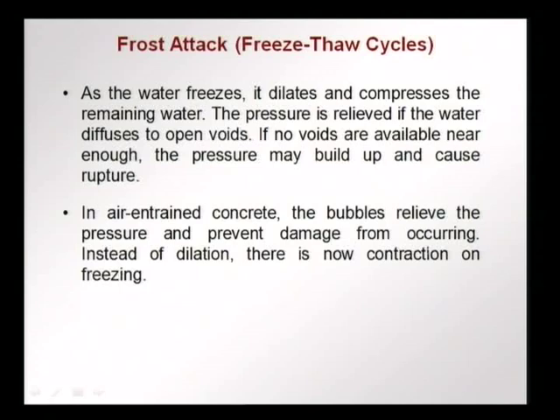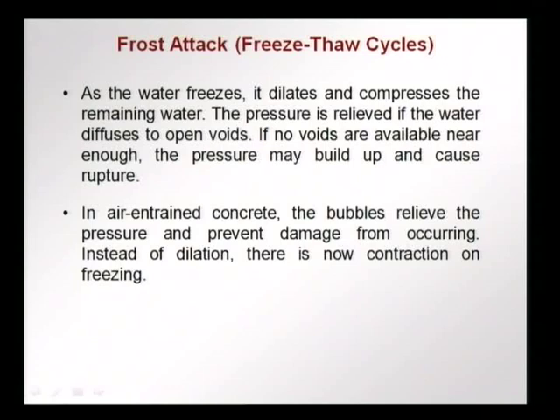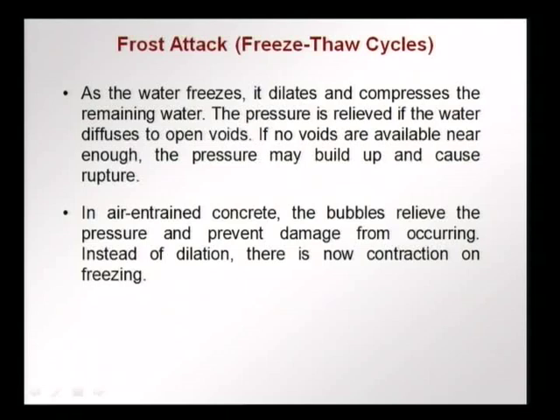As water freezes it dilates and expands, compressing the remaining water. This compression and water movement creates pressure in the capillary porosity. If there is a large void or air bubble nearby, the water is pushed into it and pressure is relieved. If only capillary porosity is available, pressure builds up and can lead to rupture, cracking in the microstructure, and ultimately disintegration of the concrete.